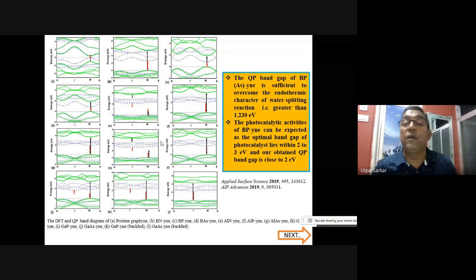Depending on this particular band gap, you can use it for applications. The quasi-particle band gaps are very close to the experimental ones, so you can believe that if you synthesize this material, it will show this particular band gap range. And the quasi-particle band gap of arsenide is sufficient to overcome the endothermic character of water splitting reactions, and it is greater than 1.23 electron volt. And boron phosphide can be expected to have an optimal band gap for photocatalyst lying between 2 to 3 electron volt, and our obtained quasi-particle band gap is very close to 2 electron volt.